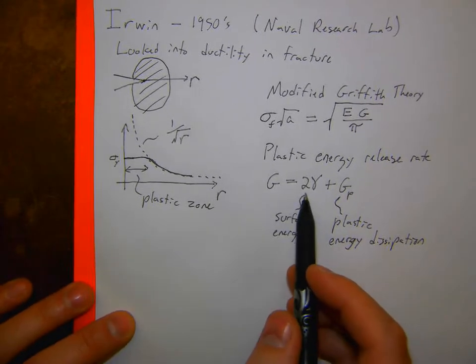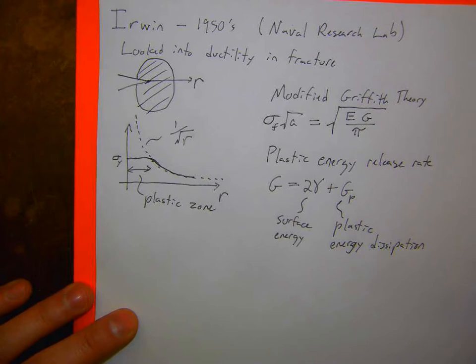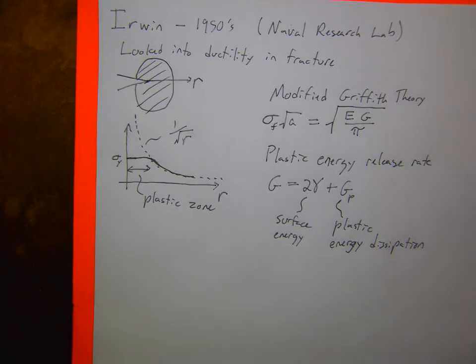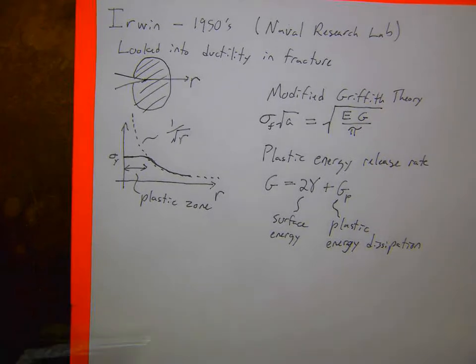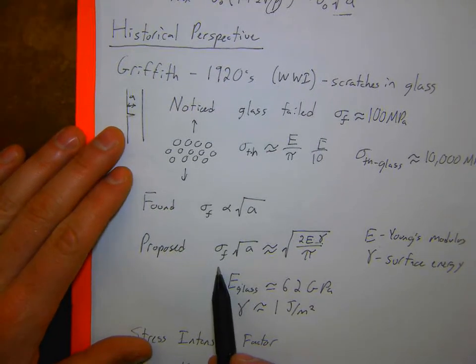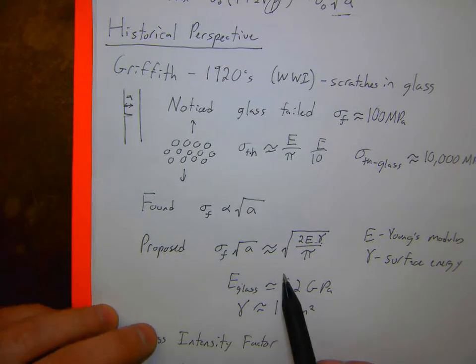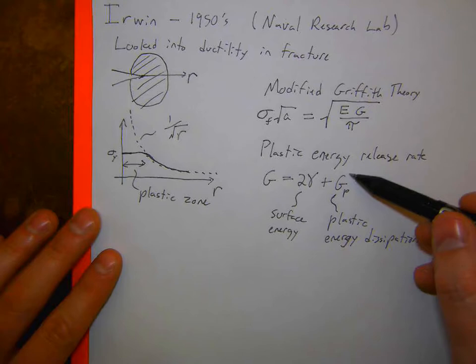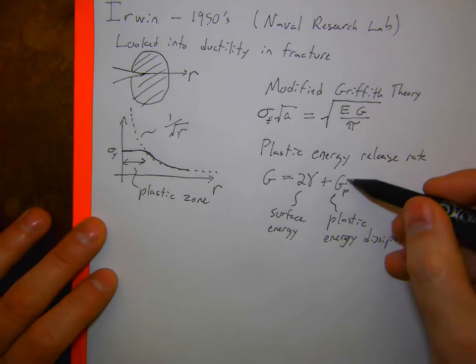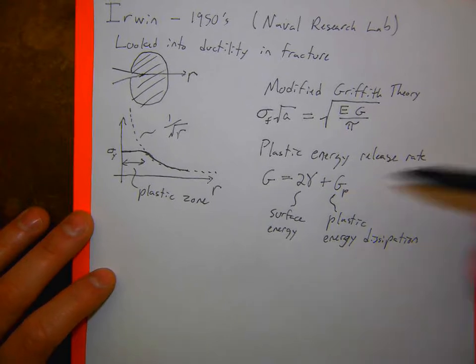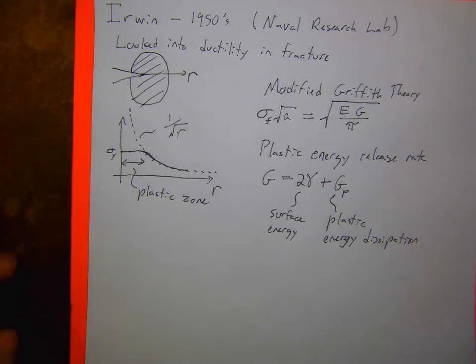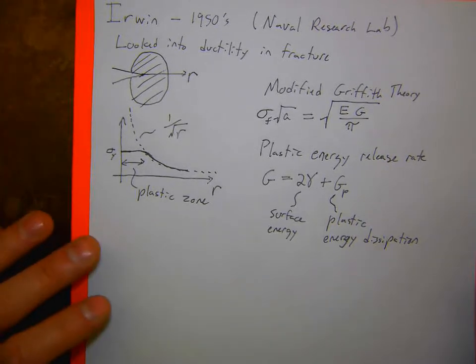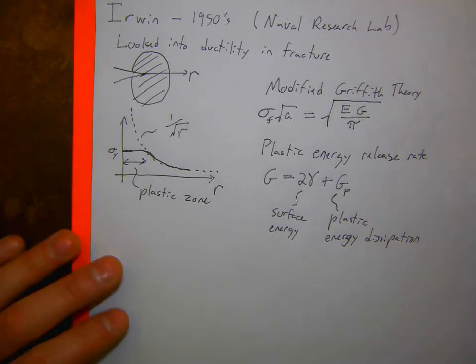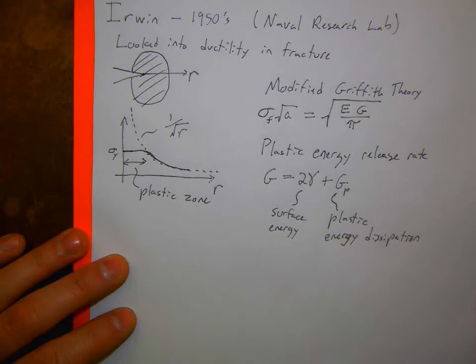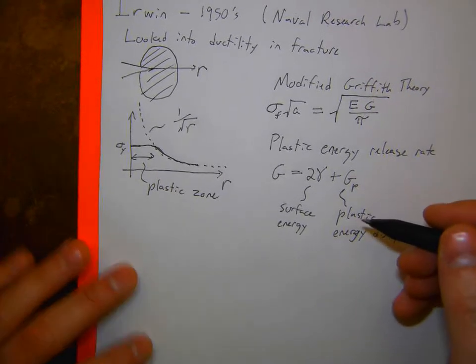And so now, in a brittle material, we actually return back to that same Griffith's theory. We still say this is square root of 2E gamma over pi. And so we still have that Griffith theory work for a brittle material. But along with that, if we have a ductile material, the ductility around the crack tip is actually absorbing a lot of energy, and that can significantly change the critical stress that you need to apply for fracture to occur. And so, okay, cool. So depending now on which material we have, this plastic energy can take place in different ways. It can form differently in different materials.